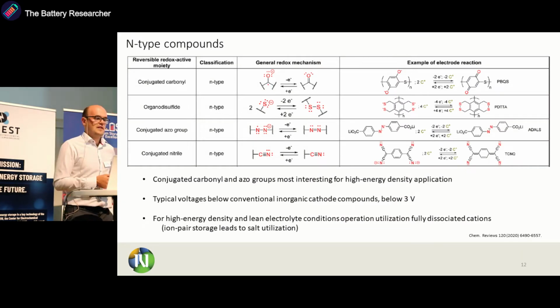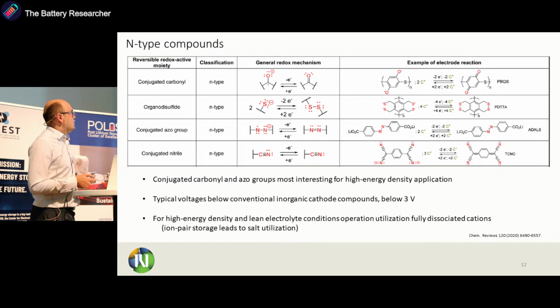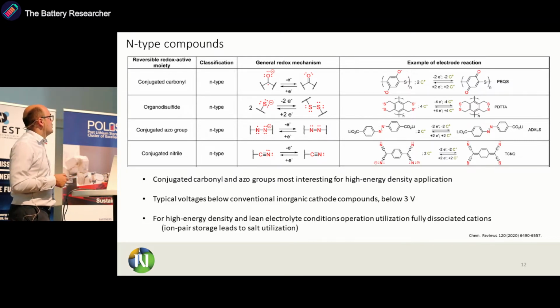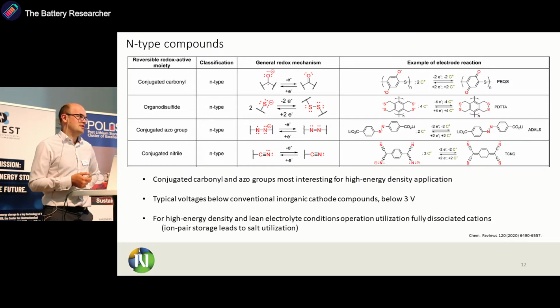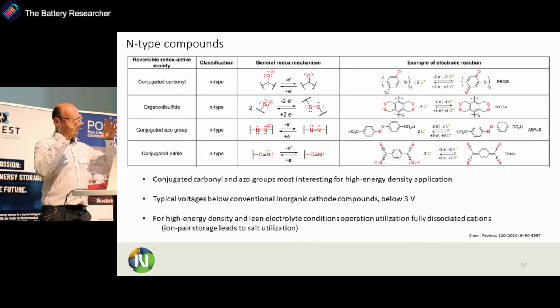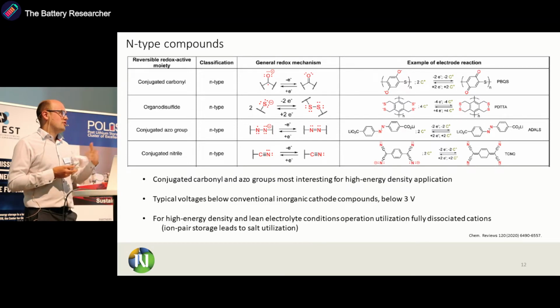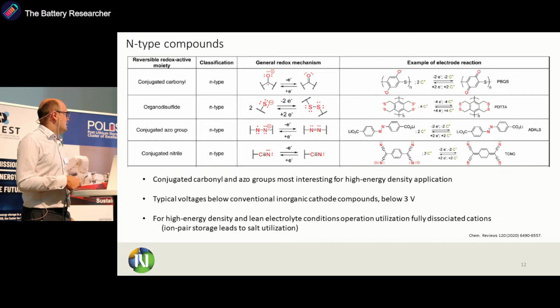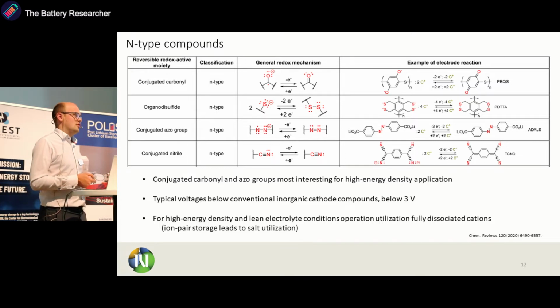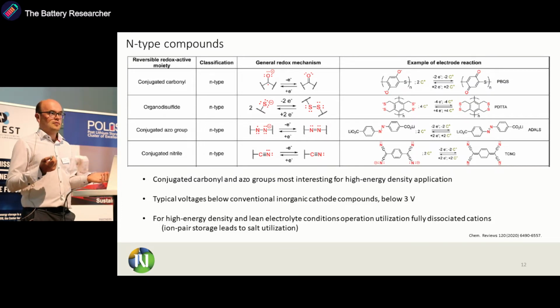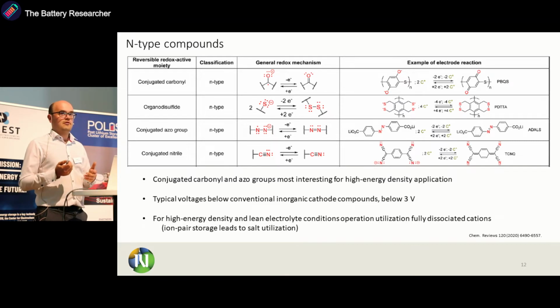If you take a look at the N-type compounds that are there, we basically have quite a few classes, and the most common are conjugated carbonyls. Then we have organodisulfides, conjugated azo groups, and conjugated nitriles. But among those, basically conjugated carbonyls and conjugated azo groups are the most interesting for high energy density application. This is because we can incorporate multiple groups in a relatively small framework, and we achieve high capacity. Unfortunately, the typical voltages of organic materials are below the conventional inorganic cathodes. So it means that the voltages will typically always be below 3 volts, which in multivalent battery research is kind of a good thing because we don't have really high voltage electrolytes.